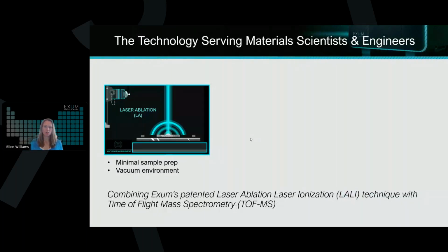The way this works, we have that laser ablation step that comes in. We have that first laser that hits the sample perpendicular to it and ablates or removes on the order of tens to hundreds of nanometers per laser pulse. This is done in a vacuum environment, so we're able to measure some of the interstitial elements like carbon, nitrogen, and oxygen that are traditionally very challenging. Being in a vacuum environment also means that we can analyze things that may be air or moisture sensitive.